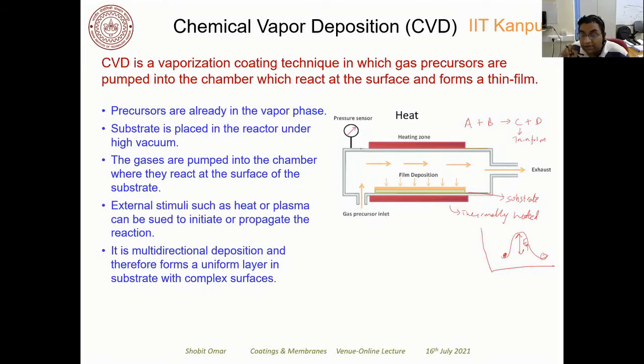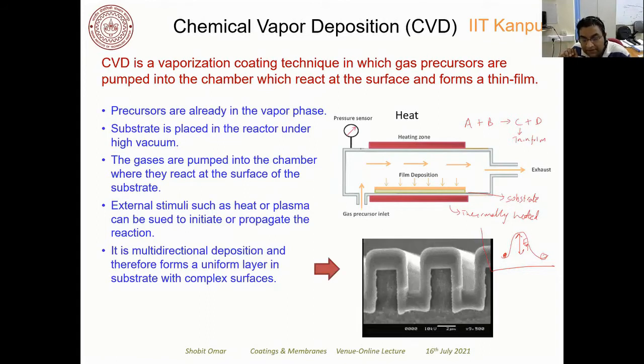It is a multidirectional deposition. So PVD normally occurs as a unidirectional, highly directional process where vapor is going from the target to the substrate, right? Only in one direction. But CVD is a multi-directional deposition, and even if you have a curved surface of a substrate, then the deposition is occurring uniformly with the same thickness. Okay, so this is one of the advantages of the chemical vapor deposition technique, that you can coat any type of surface, and you will get a uniform layer. Even if you have some type of grooves here, even after having that, you will have a uniform covering of the coating that you will have using the CVD process.